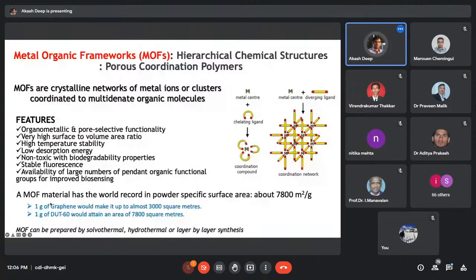Then they are highly temperature stable. They are stable up to 300 degrees Celsius, 400 degrees Celsius. Their structure remains intact. They also have low desorption energy. In sensors or in any application, this is very important, because once you utilize this molecule for the capture or for the sensing of any analyte, you also need to regenerate it for multiple uses. Once it captures something, we should also be able to get that analyte released from the molecule so that it can be reused again. And this low desorption energy means we can get the analytes out of this structure using low energy. This provides a very commercial feasibility and viability to this type of structure.